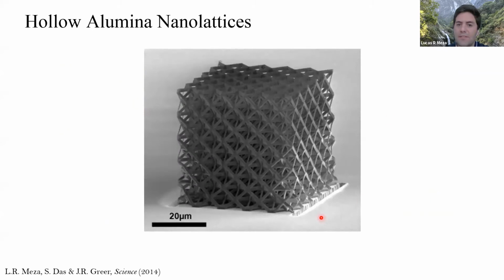Here, this is the structure that we actually make. This is an SEM image. You can see the trench marks here on the side — that's the FIB mark from exposing this. You can see the scale bar at the bottom is 20 microns. This whole thing is about 50 microns across.